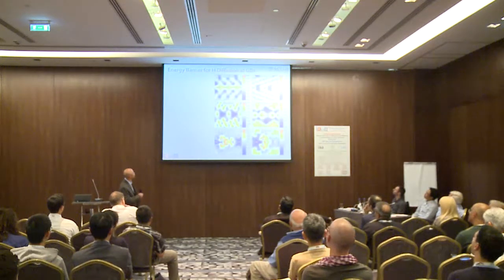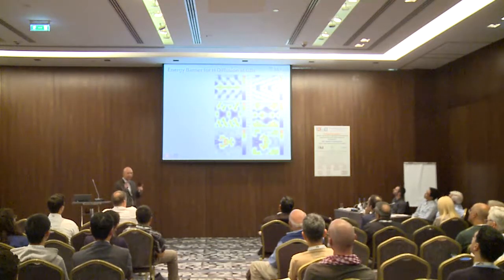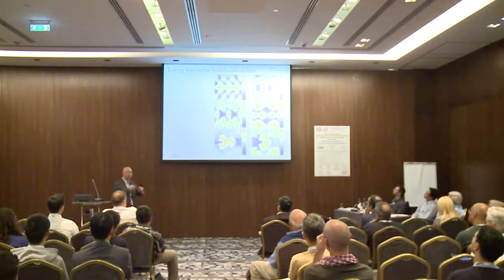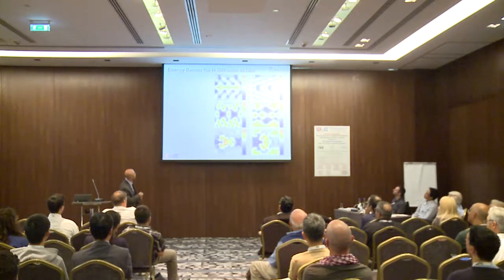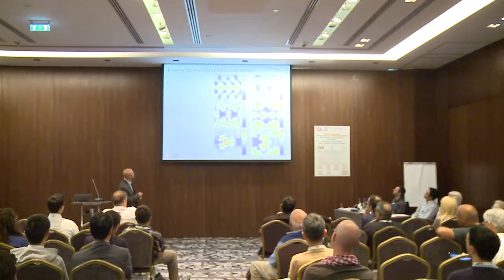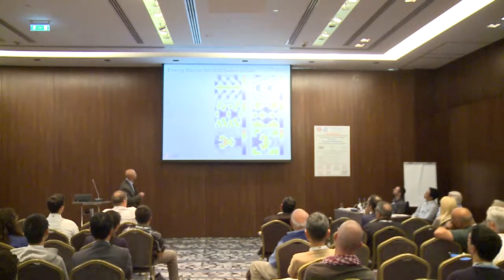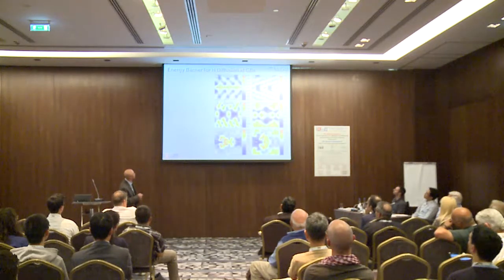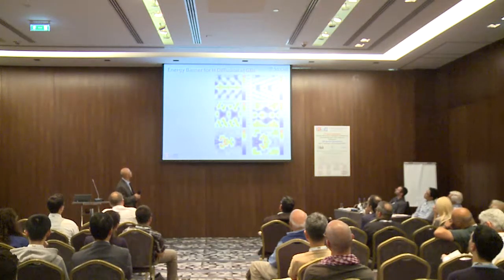One thing I want to mention is that those pictures all include a complete period of the grain boundary, so it's not localized. So this is a contour map. Since it's periodic, if you look at the different grain boundaries and the numbers, for the first two you see the barriers are more or less throughout the grain boundary similar to the bulk barrier.